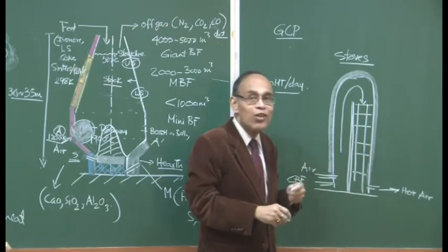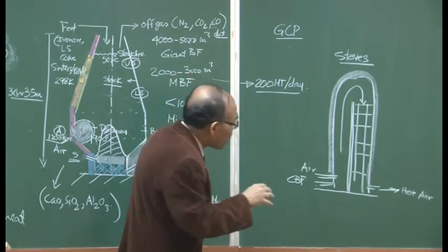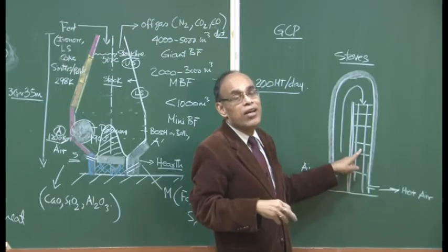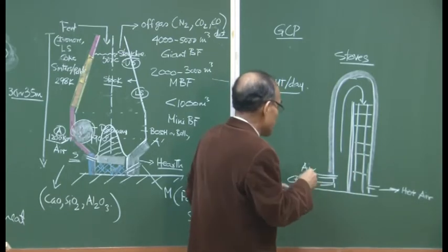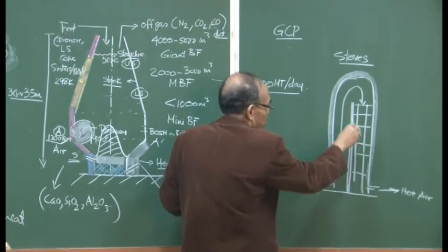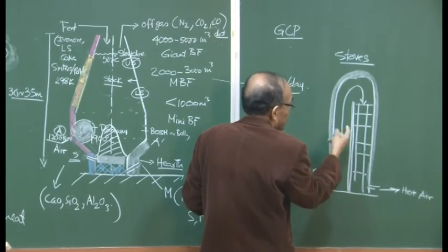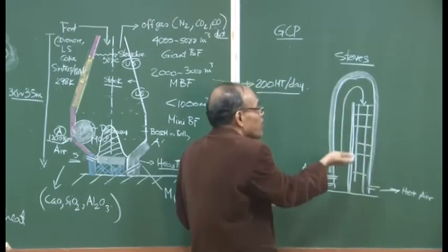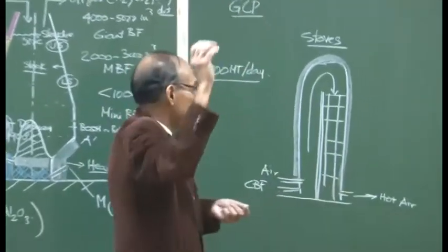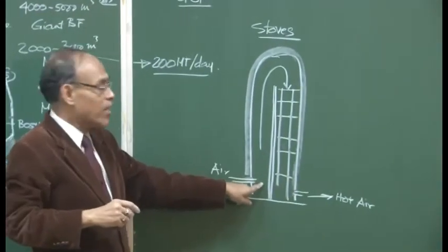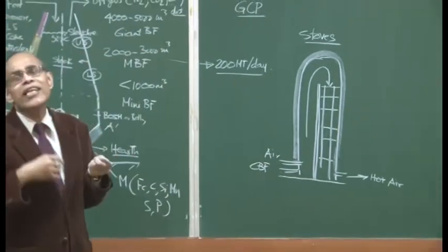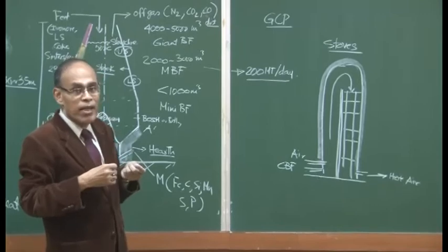Okay? And as a result of which, what is going to happen? After some time, this is going to attain a steady state where the maximum possible temperature, which could be the combusted gas temperature, is reached. If you can create 1200 degrees, 1300 degrees centigrade, then the same temperature can be created in the bricks. So, progressively the brick temperature will rise and attain its maximum value depending on what kind of temperature we have generated. So, after operating about 2-3 hours, then what happens?